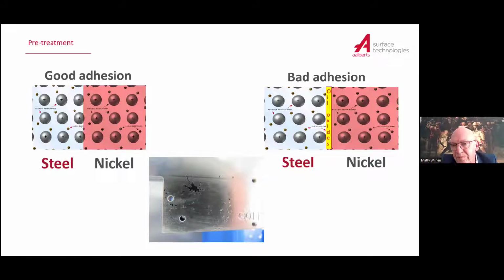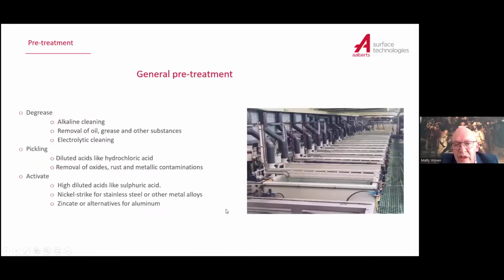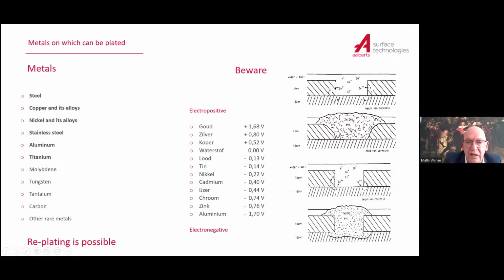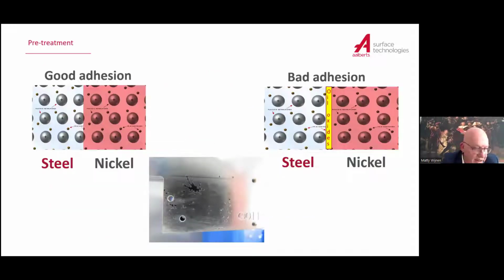This layer of oil and oxides, what you see there, is devastating for the adhesion, and it has to be removed. That is what you do when you pre-treat. If you see the bottom picture, you see that adhesion is not that good. If you see a bad adhesion, you see this kind of filaments, those small blisters, just where there's no adhesion, probably due to oil, grease, or other oxides.